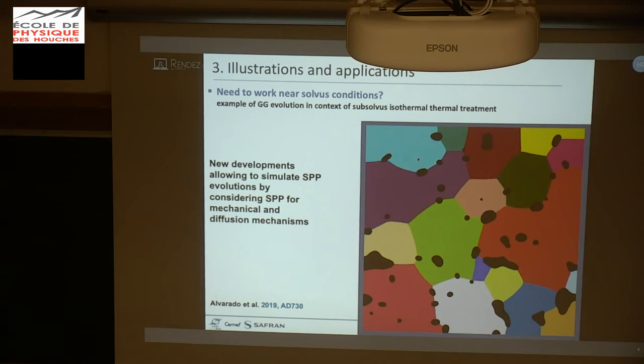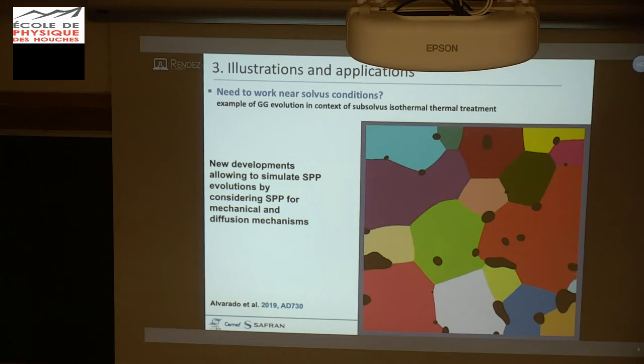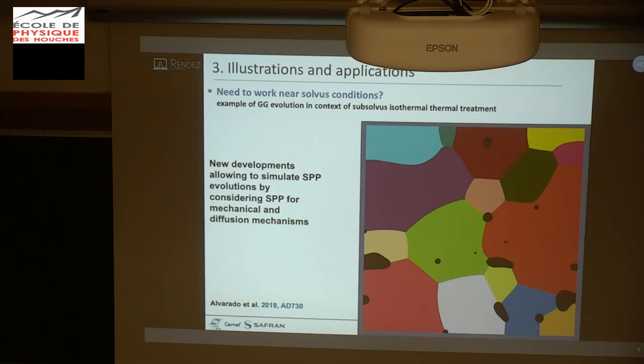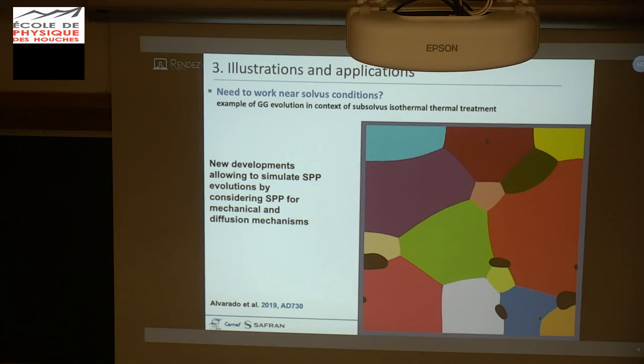And you can see some recent simulation realized by one of our PhD students, Karen Alvarado, where you can see in black the second phase particles, which evolved due to an increase of the temperature during the thermal treatment near solvus evolution. And you can see at the beginning some pinned grain interface, which begins to evolve due to the disappearance of second phase particles in black.